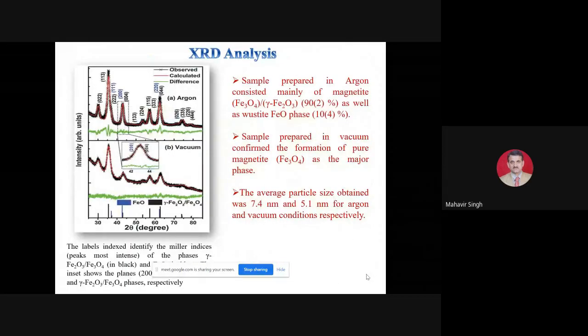So this is the approach of fabrication. Basically, this is the thermal decomposition method through which we have fabricated these magnetic nanoparticles. So this is the XRD.